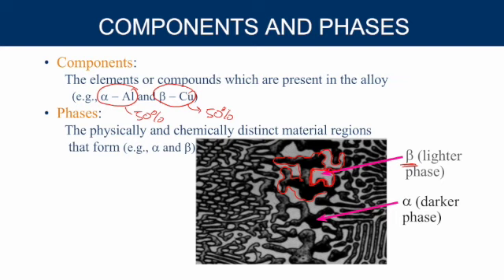So what we're saying here is that the copper dominates this phase, and that gives it its light gray color, whereas in the darker ones, aluminum dominates. So it's more than 50% in these. And this is the composition. So we can calculate the composition of aluminum and copper in each phase, as well as the weight fraction, which is the amount of each color in the image. Okay, so we're going to go over that a little bit more as we go along.